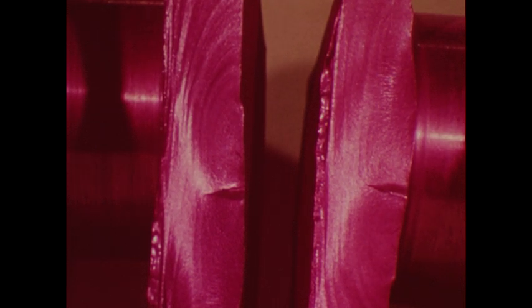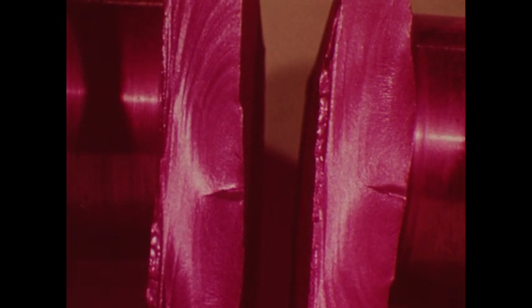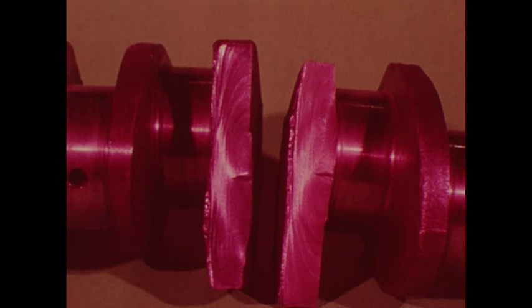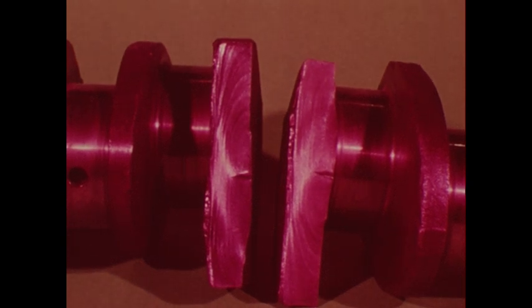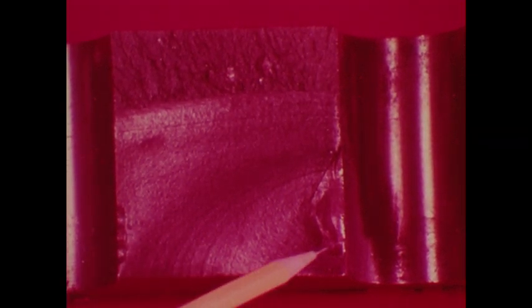Because of this sensitivity to notches, discontinuities, or even surface scratches, the crankshaft broke at the fillet. The crack in the aircraft wing attachment initiated at a bolt hole. Fatigue failures can usually be traced to such stress raisers.